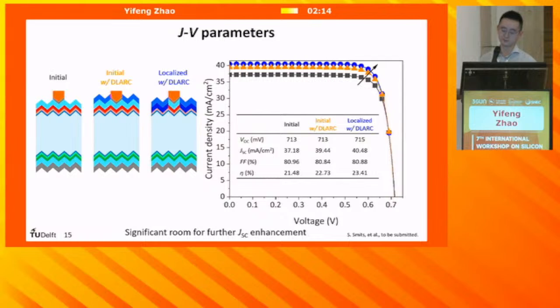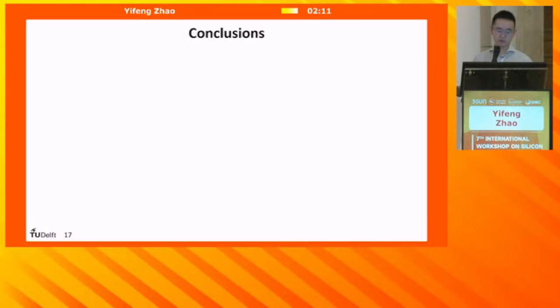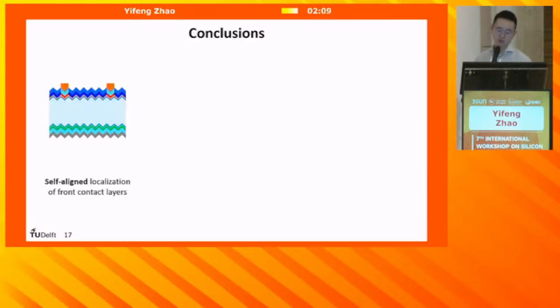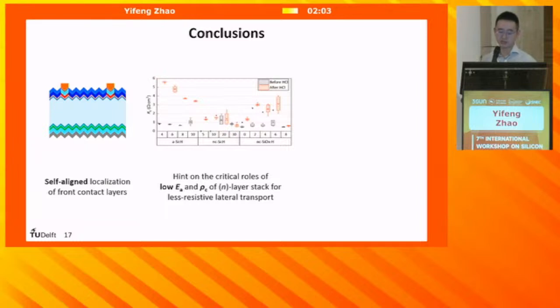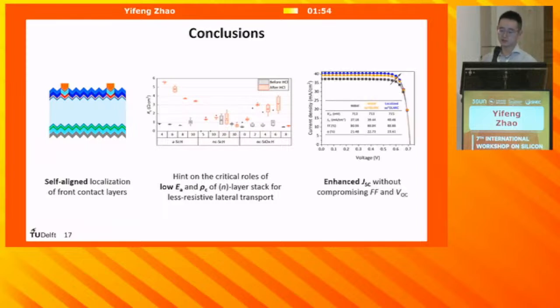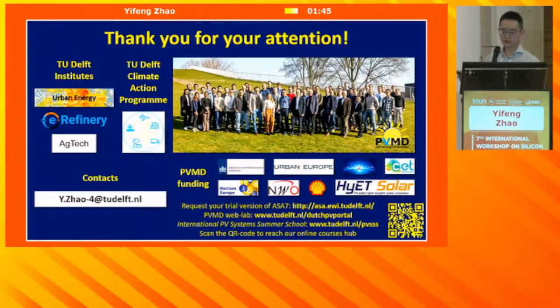In conclusion, we successfully developed a self-aligned process for localization of the front contact stacks. We also found potential critical roles of the low activation energy and the contact resistivity of the N-layer stack for less resistive transport. Lastly, we also demonstrated a solid JSC gain without compromising any fill factor or VOC performance of the solar cells. With this, I would like to thank you for your attention.